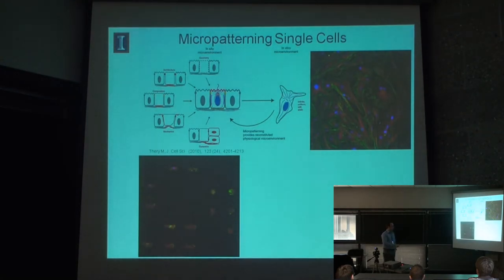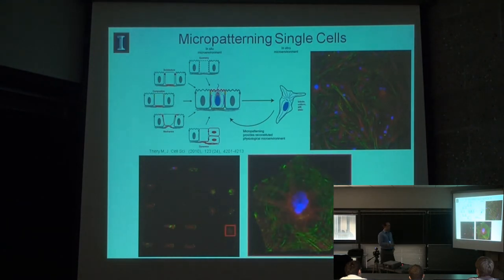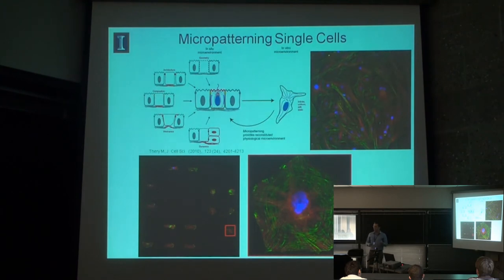Here's a picture of cells that have been micropatterned in our lab in a range of different geometries. The reason we do this is that now, instead of just changing area, we manipulate some of the subcellular curvatures and aspect ratios and things like that, and we can get very different organization of the filaments within the cell. So this is a flower shape. You see here we have the nuclei in the center, and we get this nice ring-like filamentous actin network, and this beautiful web formation of microtubules throughout the cell. By modulating that architecture, using different shapes, you can influence the way that these things align, and use this as a method to study the importance of geometry and how it influences the cytoskeletal architecture.